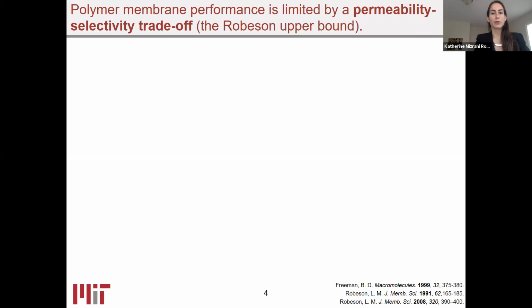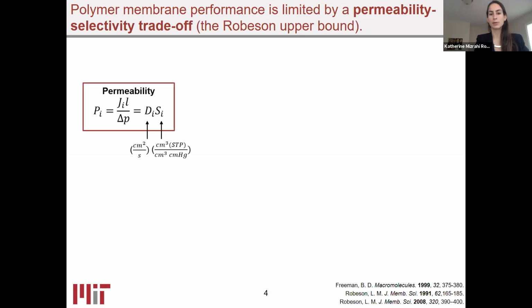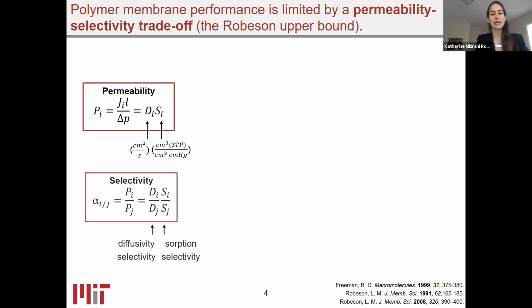If we think of membrane performance, there are two key metrics to consider. The first is the permeability, which is a pressure and length normalized flux through the film, which can be rewritten in terms of the diffusion and the sorption coefficient in terms of the solution diffusion model. And the second is the selectivity, or the ratio of the permeability of the more permeable gas over the permeability of a less permeable gas, which can also be rewritten in terms of the solution diffusion model as the product of the diffusion selectivity and the sorption selectivity.